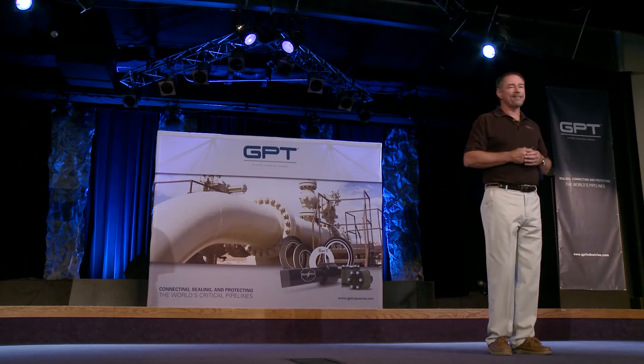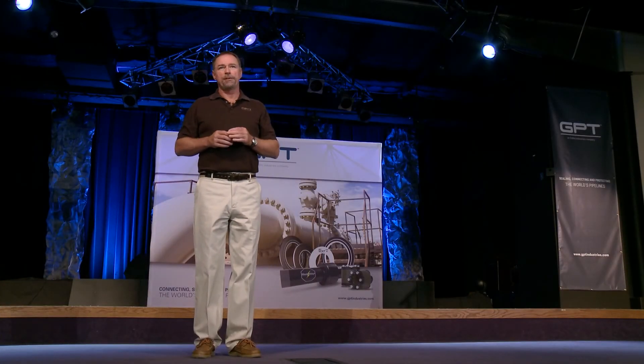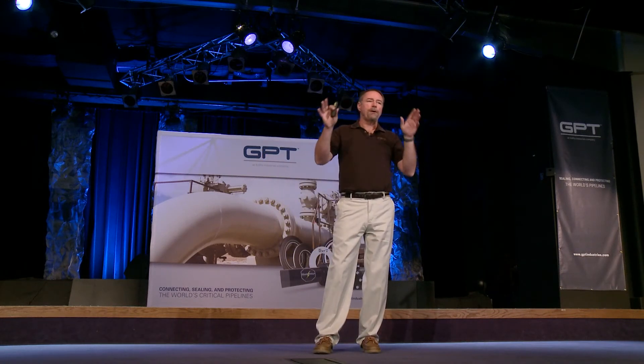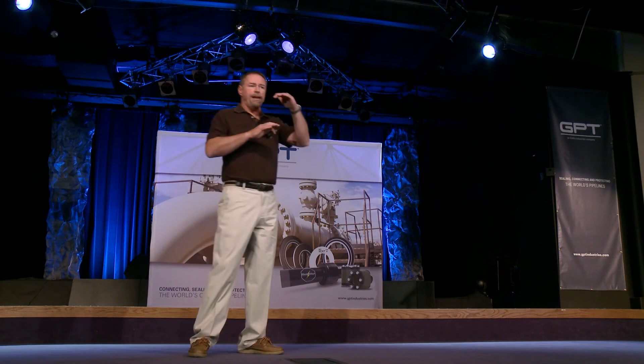Another not-so-apparent risk — and I'm surprised we've even seen it — is that some manufacturers will actually put their labels over the seal. The seal is intended to seal, but it can't seal if it's not contacting the flange because a label is sitting between it and the flange. Another issue from careless manufacturing: you need adhesive below the seal to hold it in the groove, but too much adhesive will flow outside the groove and harden. Once hardened, the glue prevents the flange from coming down on the seal, causing a leak or potential blowout.